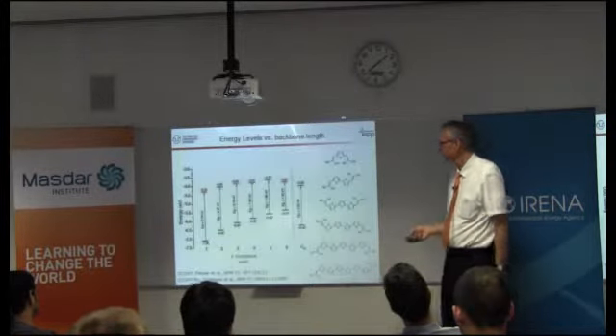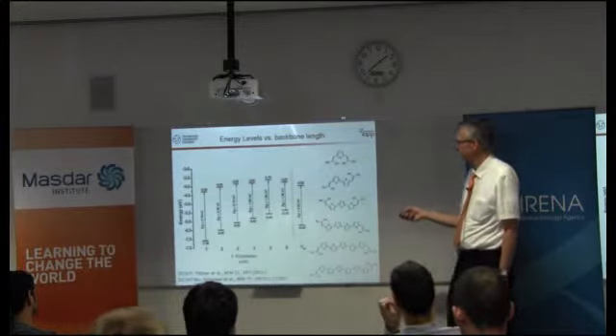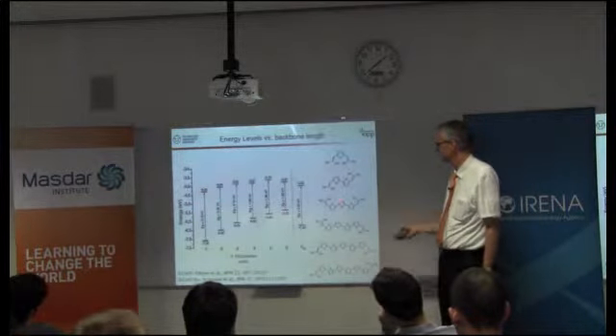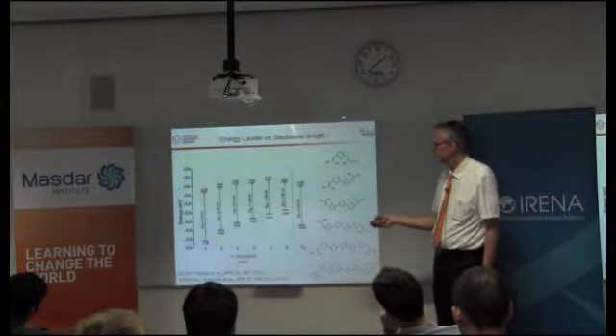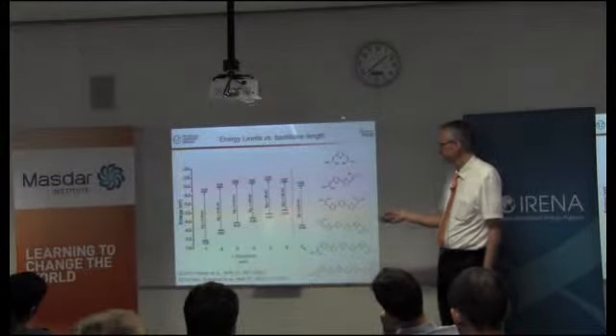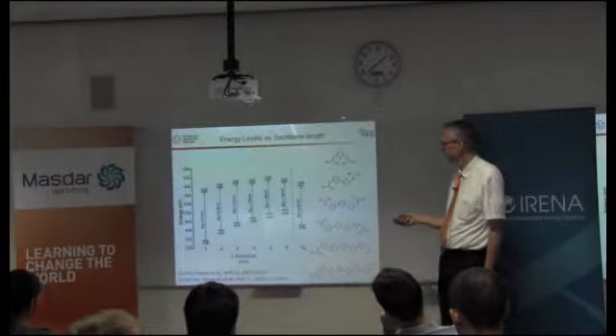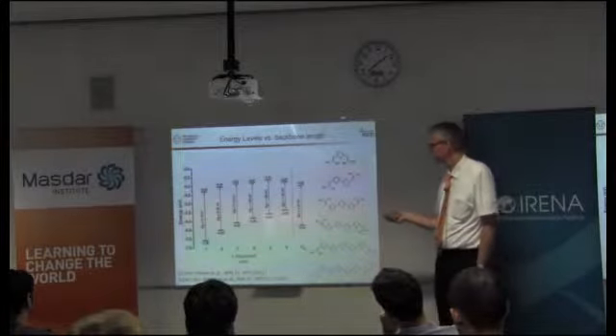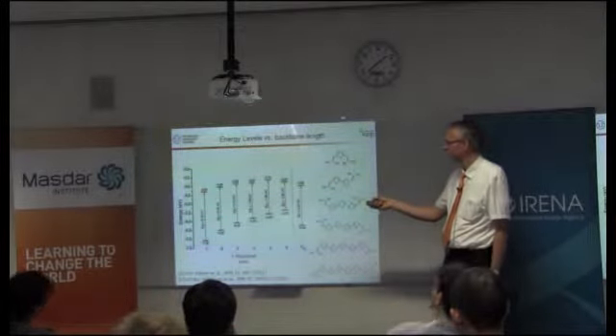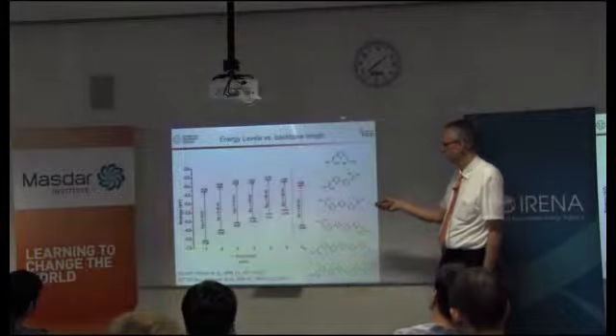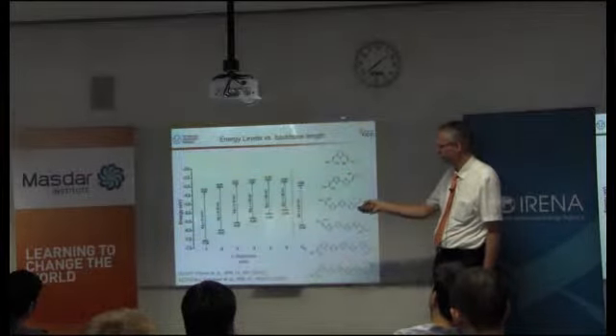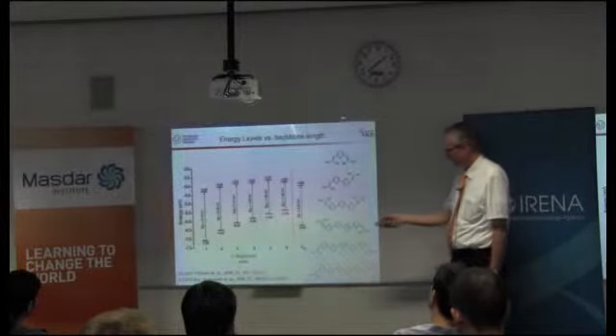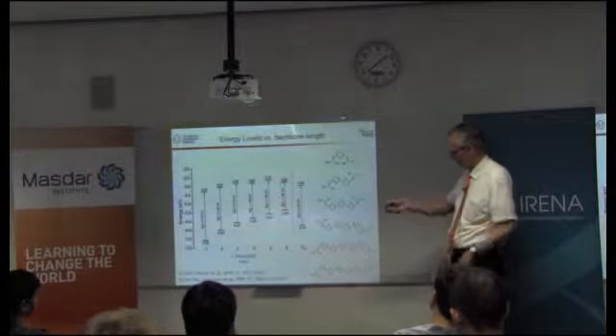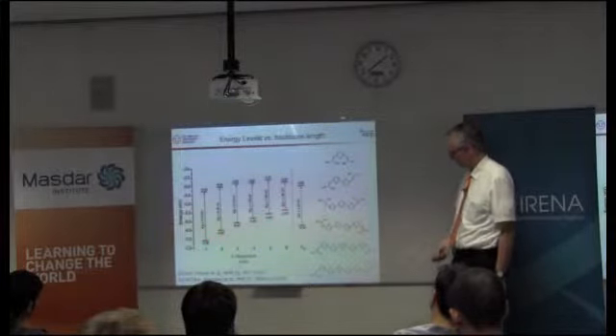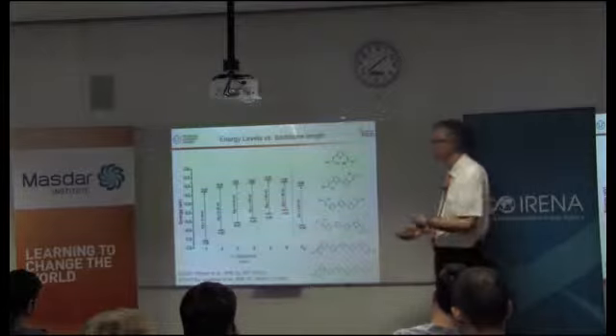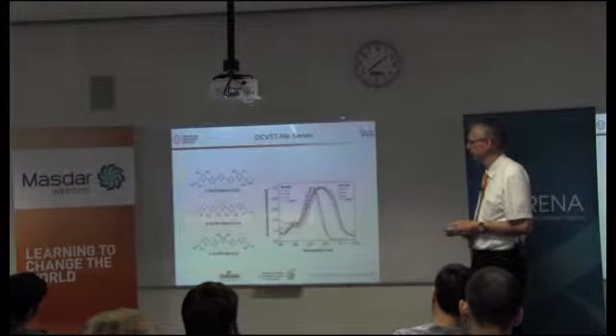And for instance, the energetics, you can nicely see that when you change the length of the molecule, the highest occupied orbital, the HOMO, is dramatically shifting upwards for longer chains, whereas the LUMO has a much smaller shift. So you change the gap from the blue to the red, and you can change for the step where the exciton is separated. This energy level is really relevant, and therefore we could really systematically look at the energetics.